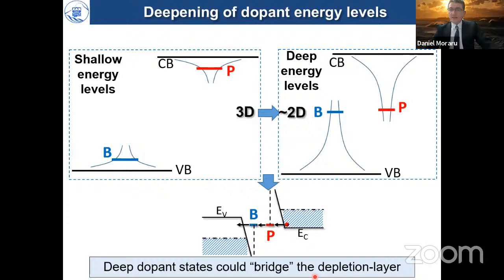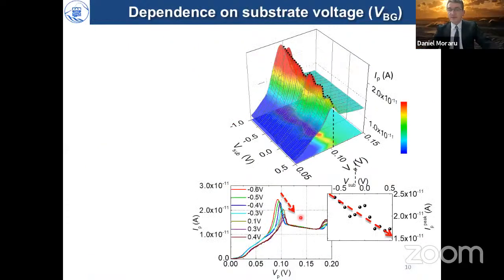So the results are shown here in different visualizations. The bottom figure shows the IP, VP, in the forward bias, and what is given in the inset is the V sub voltages. When we apply different V sub, we can shift this enhanced current peak left or right as shown by this arrow, and we can also change the intensity of a current peak. On the top, you can see the surface plot, same result, but shown as a surface plot.